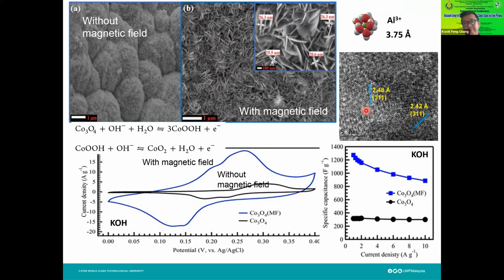And then we go and study the aluminum. We want to know, is the aluminum able to go into the crystal structure of this cobalt oxide? We tried experimentally, it couldn't. Then we ran a crystallography study and looked at it. The crystal spacing for this cobalt oxide is in the range of 2.4 angstrom, which is smaller than the 3.75 angstrom possessed by the aluminum ion. So once again, we failed. We couldn't put our aluminum ion into this cobalt oxide. But nevertheless, we are able to find a method whereby we can extract the cobalt oxide.